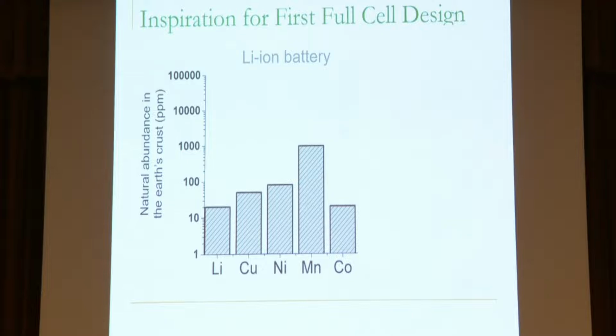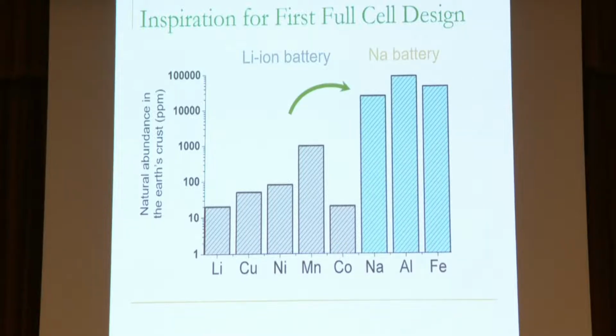And in fact, we use it in batteries already. So if you go to the store and you get a lithium primary battery, so it looks like a AA battery, but it says lithium on it, it has iron disulfide in it. And the beautiful thing about this is that when we think about transitioning from a lithium battery to our sodium battery, if we use this as our cathode, the only materials that we have in this are sodium, aluminum, which is our current collector, and iron. That's it. Oh, we have sulfur too, but sulfur's cheap. As opposed to things like cobalt.